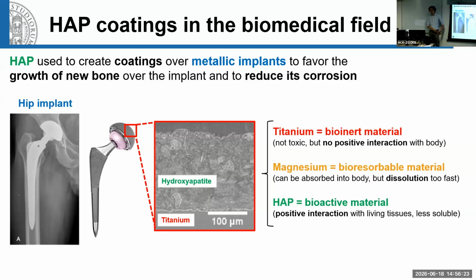Here is problems at the hip, where people need metallic implants made of usually titanium, which is usually or always covered with a thin layer of hydroxyapatite, because this hydroxyapatite is a bioactive material. It means that cells in our body recognize this hydroxyapatite, and in this case, also the titanium implant covered with hydroxyapatite, as something friendly to our body. So the cells and the new bone is able to grow over or through this hydroxyapatite layer.